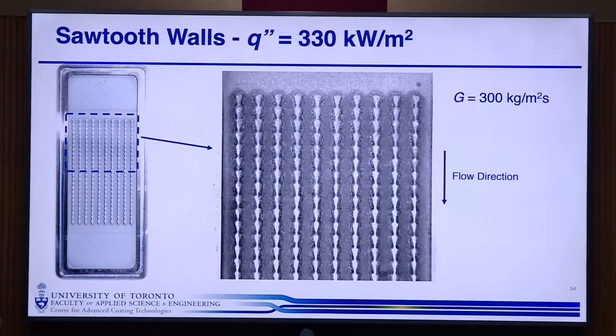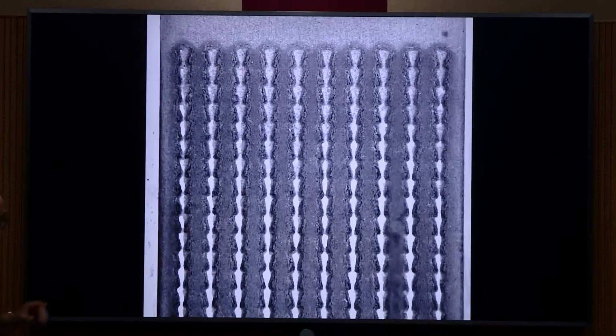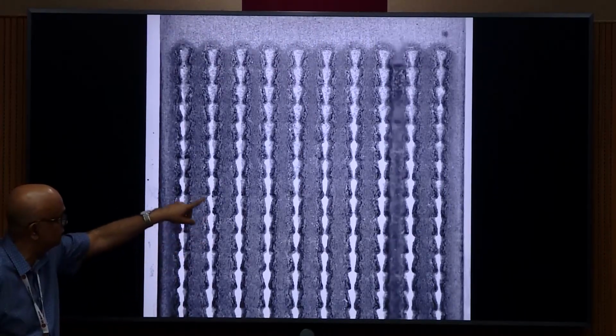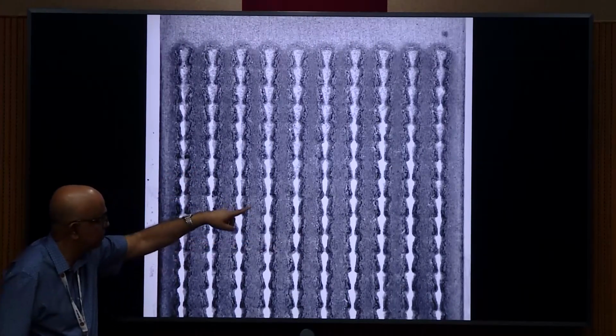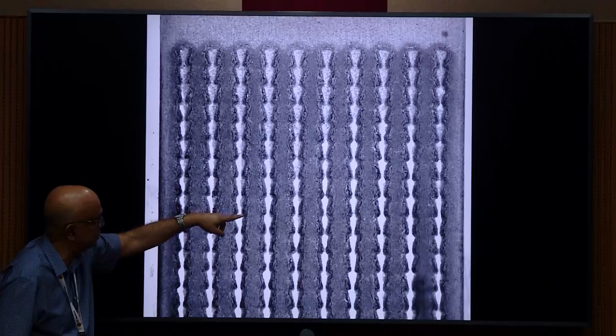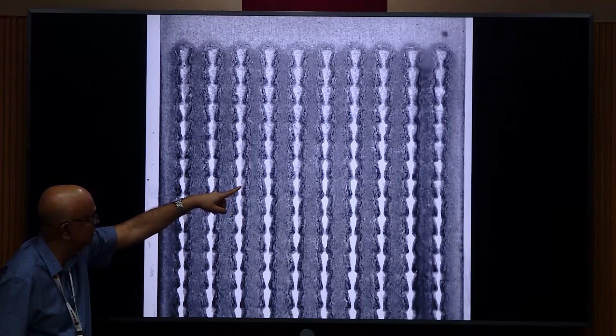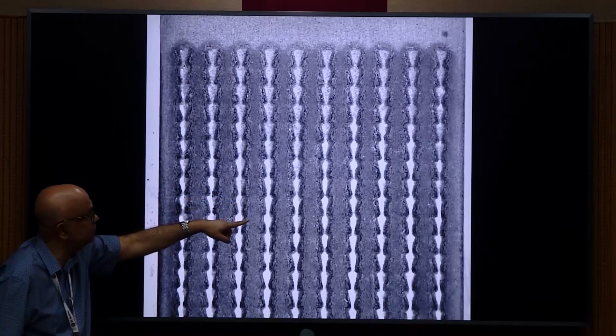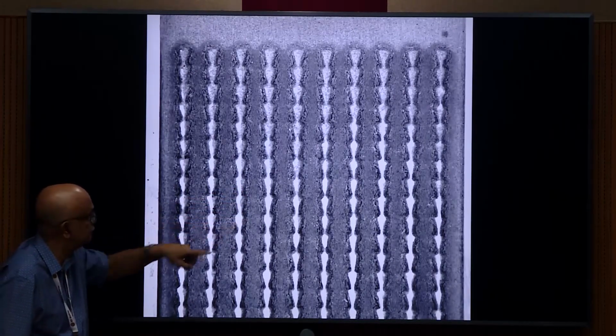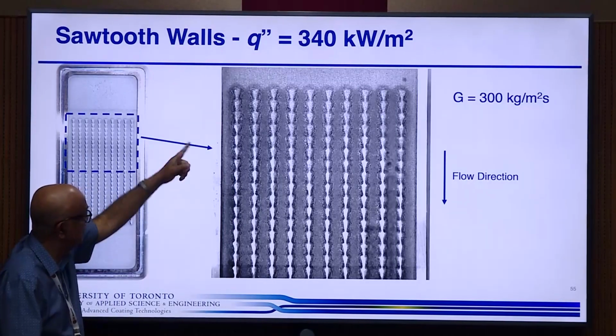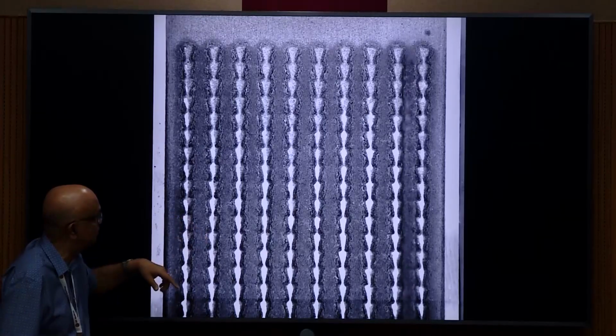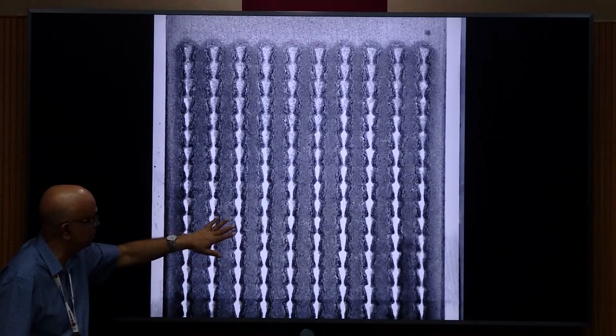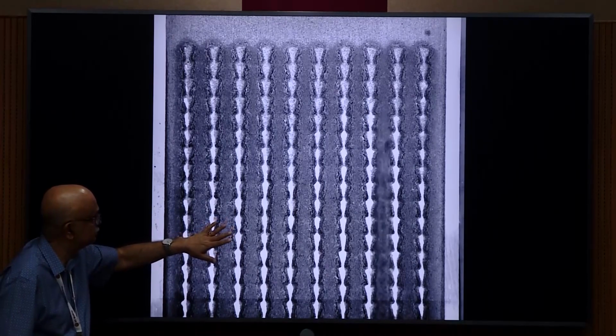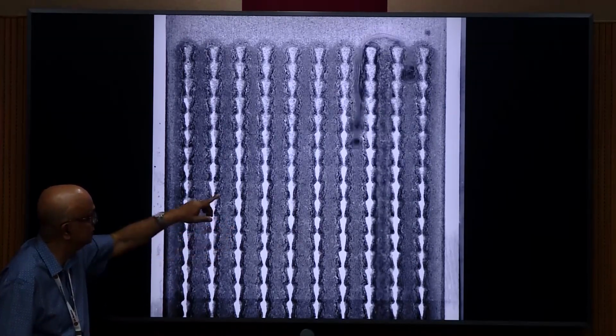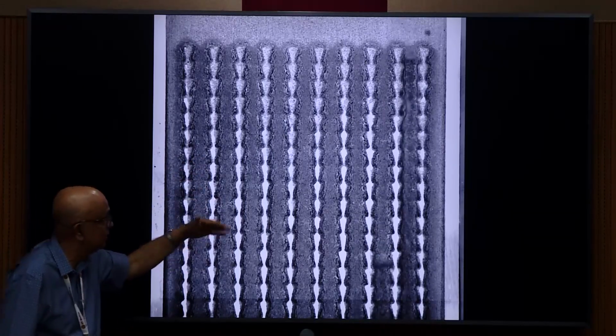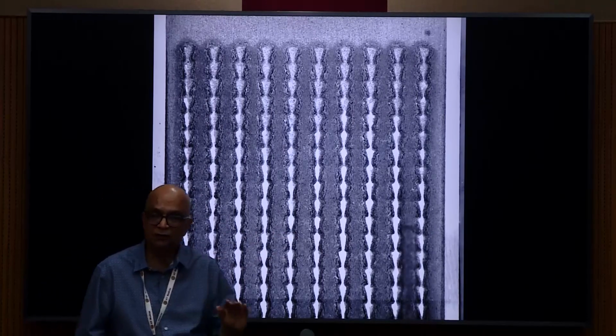And so now we go back and we test this. And so now we are right at that limit, you know, where we are getting dry out. But now look what's happening over here. The liquid is actually trying to push that down. So you try and get dry out, and it actually looks like it's being pushed down. And that was at 330, we increased this up a little more. And now you can see it's becoming harder and harder to push it down. Okay, and you can see the instability, but we are right at the limit of before we get the instability.